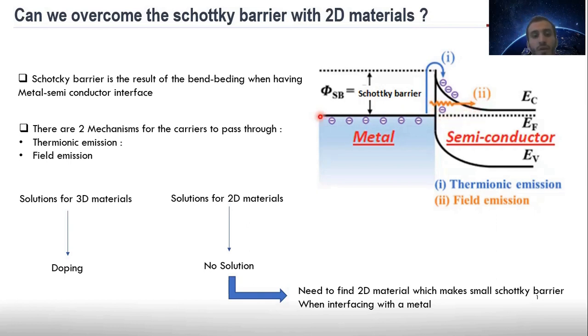One solution for 3D materials to overcome the Schottky barrier is to use doping. However, for 2D materials, we cannot use doping since you will destroy the crystal lattice and you will introduce defects. So the only solution is to find a 2D material which makes a very small Schottky barrier with the metal.